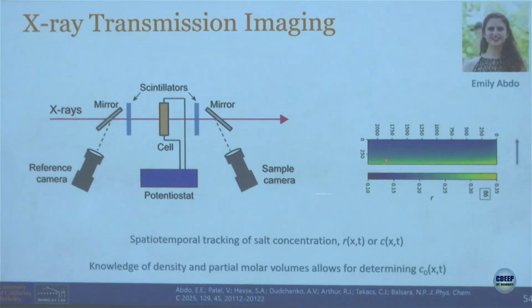And let's see if that happens. You'll see this is flat at t equals 0, and then as you polarize the cell, you get concentration growth at one end and concentration decay at the other end. So this concentration, which was initially something like 0.2, if I remember correctly, you get 0.35 on one side and 0.1 on the other side.